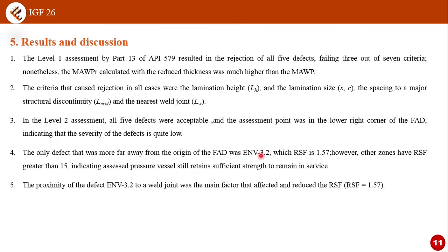non-metallic inclusion zone that is so close to the weld joint, and this causes the remaining strength factor to be reduced. However, other zones have a remaining strength factor greater than 1.5, and the proximity of this non-metallic inclusion zone to the weld joint was the main factor that affected and reduced the remaining strength factor.